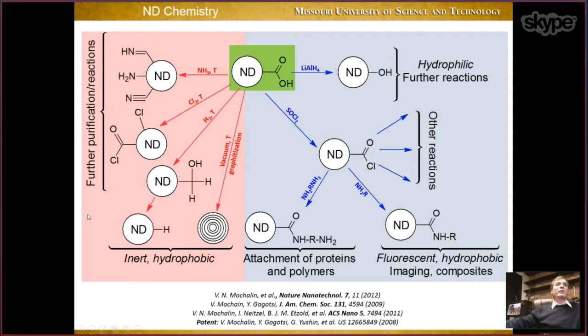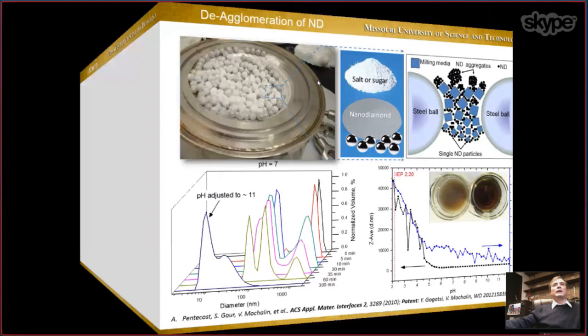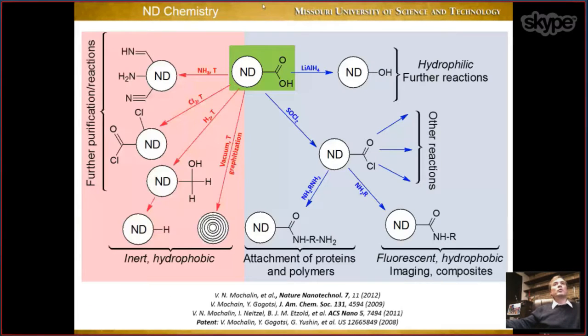You can use, for example, high temperature gas chemistry, basically anneal this nanodiamond in different gases: ammonia, chlorine, hydrogen. You can even anneal it in vacuum at high temperature. By doing this, you convert nanodiamond into carbon onions. So basically, you convert sp3 material into sp2 material. Or you can use wet chemistry techniques and, for example, reduce carboxyl groups with a reducing agent common in organic chemistry. You'll get hydroxyl-terminated nanodiamond. If you treat it with thionyl chloride, you can produce acyl chlorides. So it's nothing new. It's basically known chemistry of carboxyl groups applied to nanodiamond.